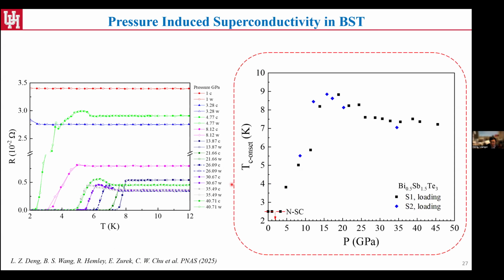First of all, we mapped out this TC-P phase diagram, and we saw that around 5 GPa it turns from non-superconducting to superconducting, and then there's a kind of gap. It jumps above 10 GPa, reaching around 8 to 9 Kelvin, and then is followed by a slight drop, and then remains almost a plateau above 25 GPa.